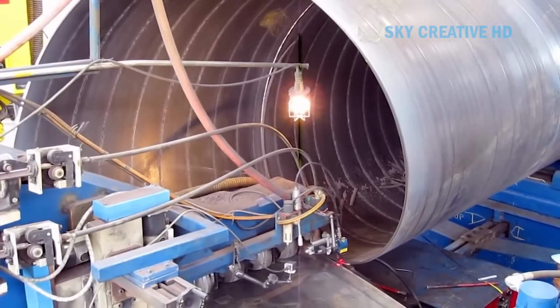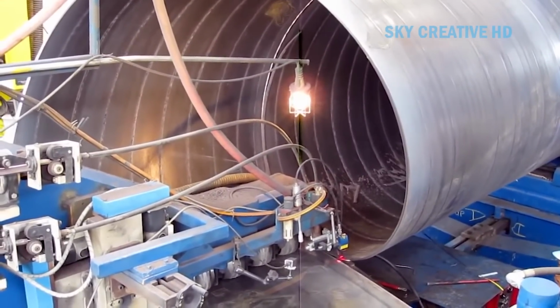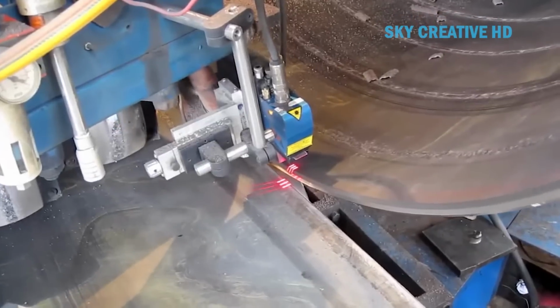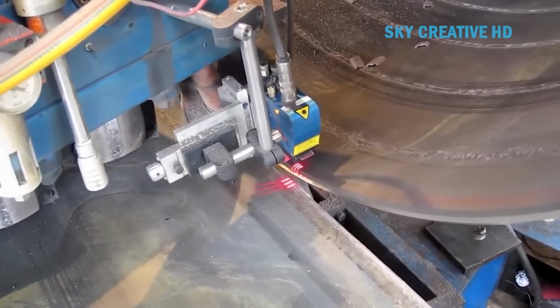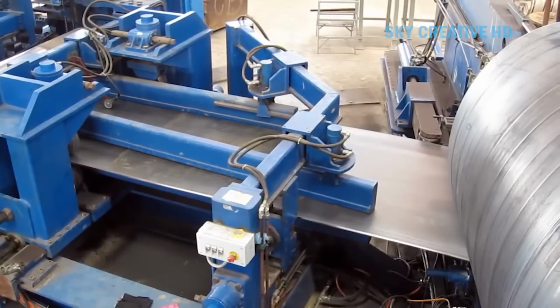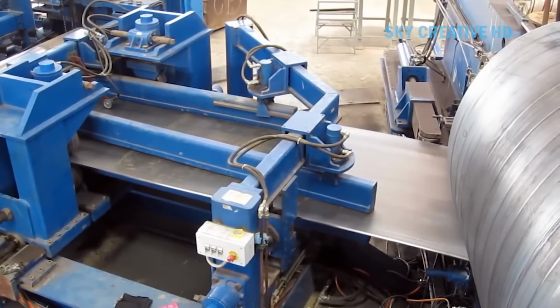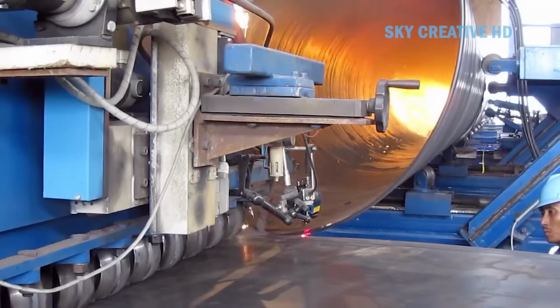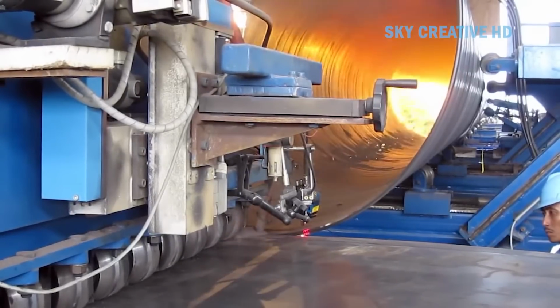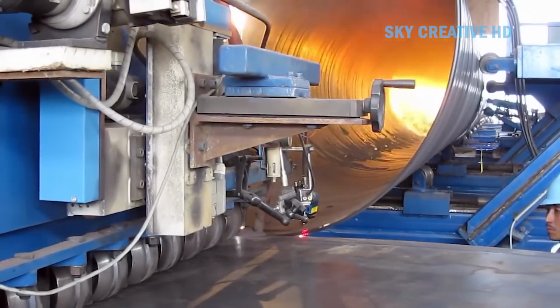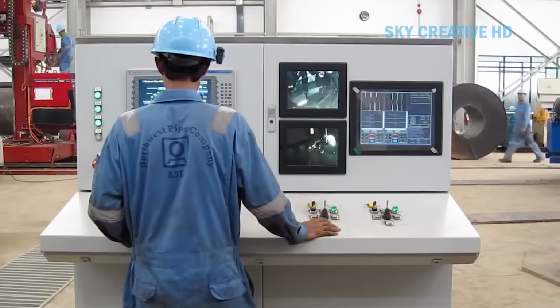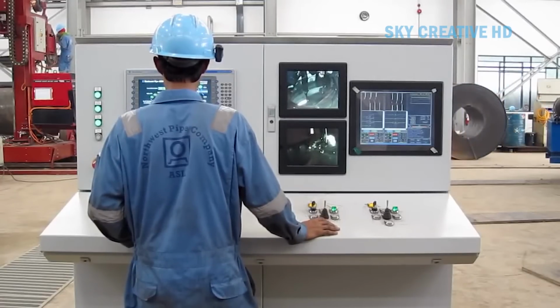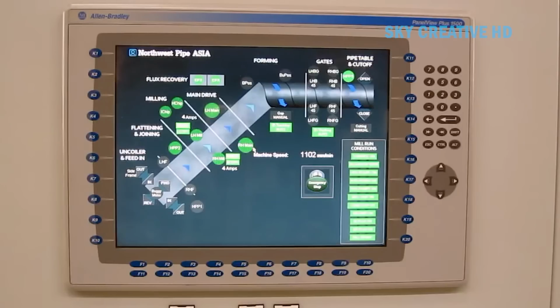The heart of the operation is the helical forming stage, performed by the forming mill or spiral pipe mill. This machine utilizes a series of precisely positioned rollers, arranged in a cage-like structure to progressively bend the steel strip into its helical shape. These rollers, categorized as inner and outer forming rollers, are often driven and synchronized, with guide rollers maintaining the correct helix angle. Crucially, an angle adjustment mechanism allows for precise control of the helix angle and thus the final pipe diameter. A powerful drive system pulls the strip through the machine.